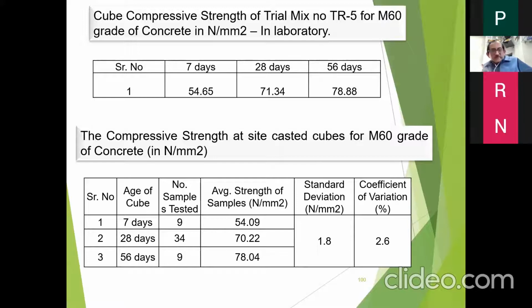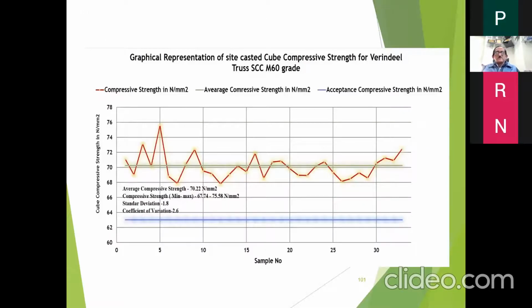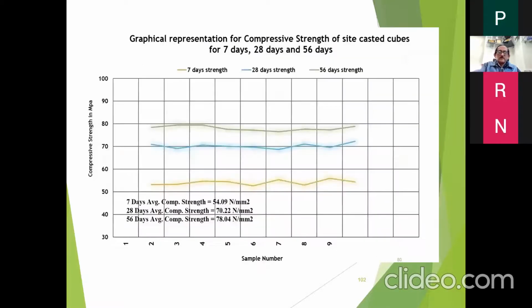Also, at 56 days there would be a gain in strength, and you can see almost 10%, 11% increase in the strength from 28 to 56 days. This is the graphical representation of the 7 days, 28 days and 56 days compressive strength.